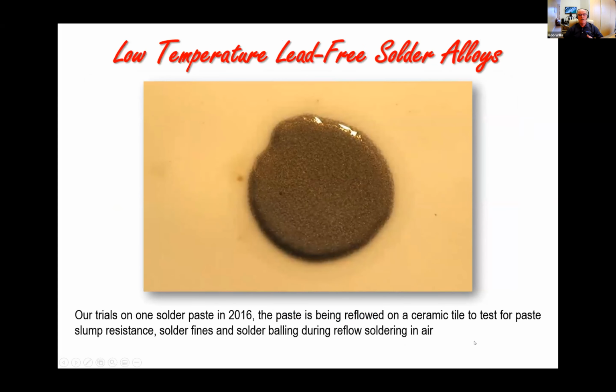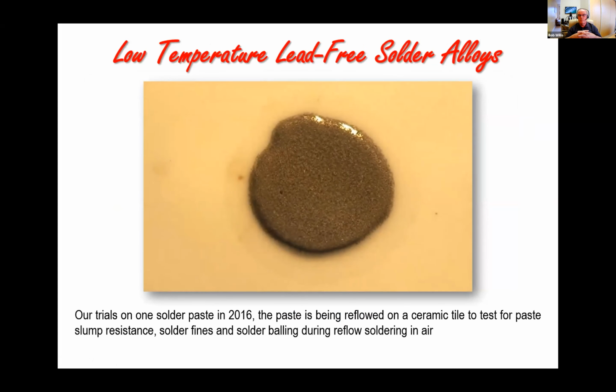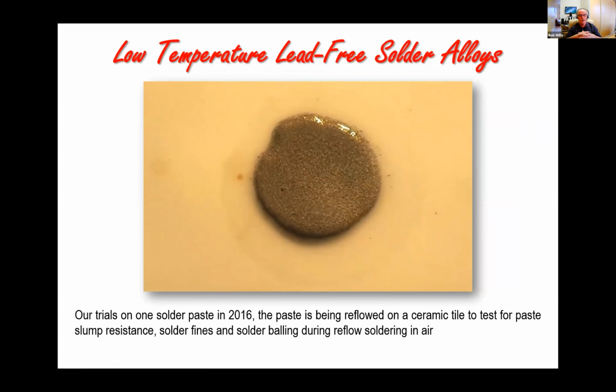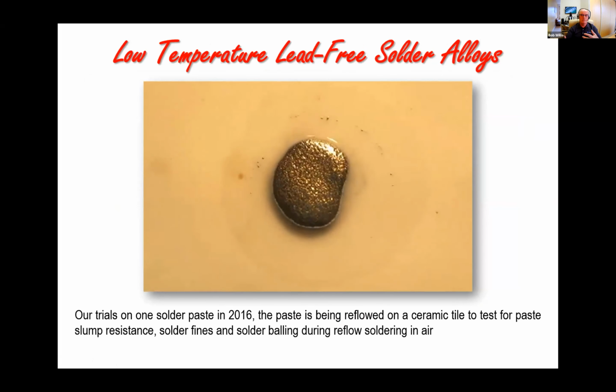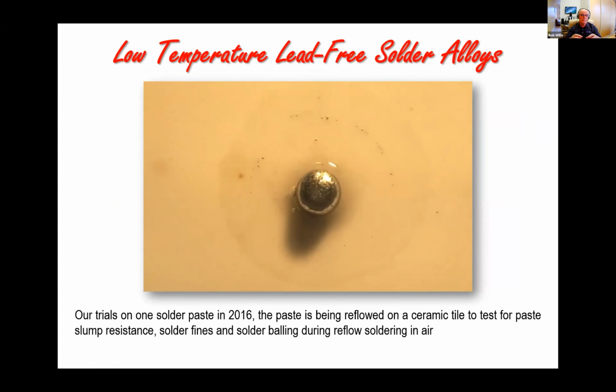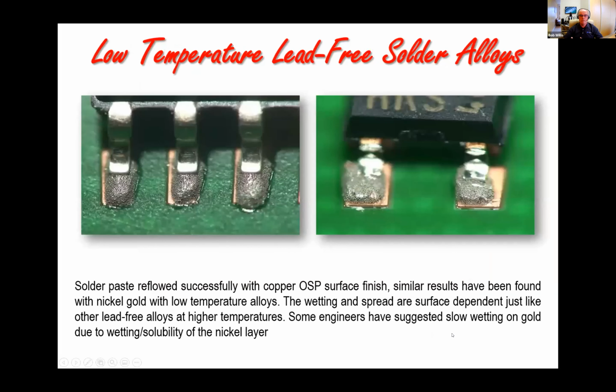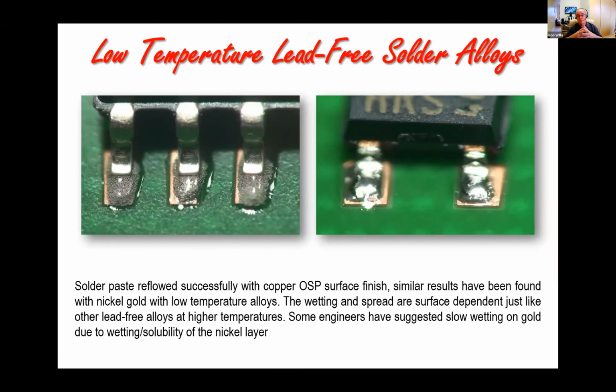So in 2016, originally, I was doing some more trials on low temperature materials, and like an engineer, I like to understand what the materials are and how they react. So we did reflow trials, solder balling trials, slump trials, all the usual things that we would do to assess a product. And this is just an example. The materials had improved quite a lot from the early days. We built boards with both nickel gold and copper OSP, and the two examples I show here are on copper OSP substrates.